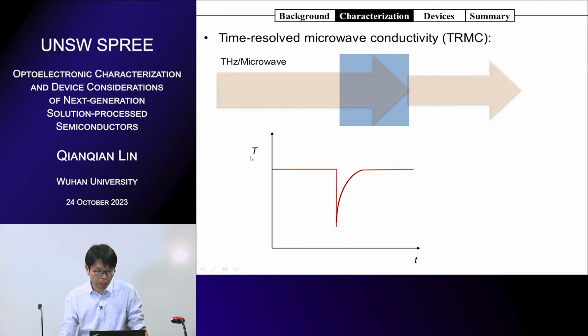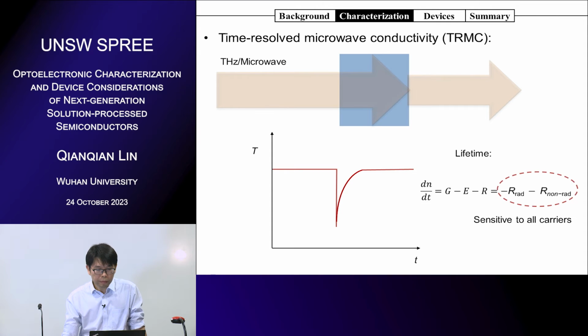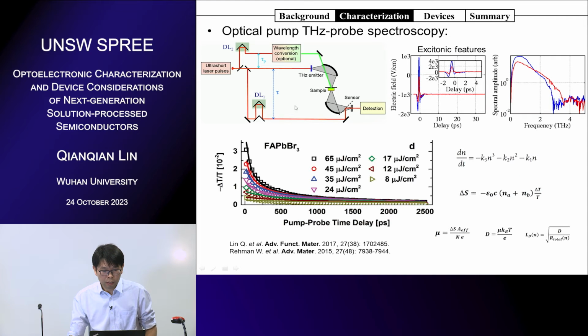So if we can record the transients of this transmittance or reflectance, then we can get the time-resolved microwave conductivity or terahertz. And the decay mainly depends on the recombination processes. And for this measurement, we get all the information of radiative and non-radiative sites. So the recombination is dependent on all the carriers. So if it is an intrinsic semiconductor, this decay more or less overlaps well with TRPL. But for some materials, like heavily doped ones or with a lot of trap states, the decay will be quite different because the majority carriers will dominate the decay, not like the minority carriers. So this is the mechanism of TRMC.